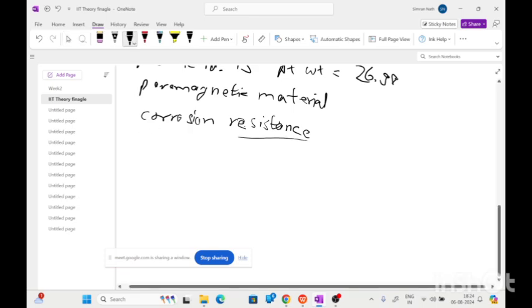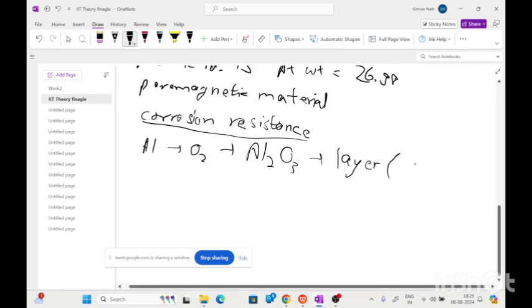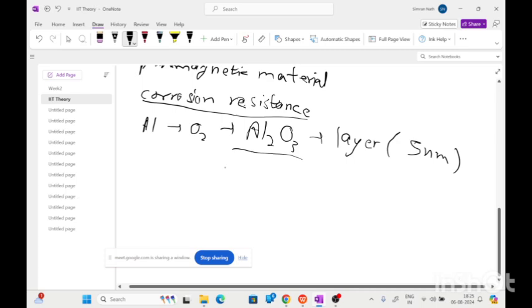So how does aluminium have high corrosion resistance? Aluminium has a tendency to react with oxygen to form aluminium oxide, Al2O3, readily. When the Al2O3 layer forms on the aluminium, it is a very adherent and impervious layer of thickness 5 nanometer. The adherent layer of alumina inhibits further corrosion of the component, thereby providing good corrosion resistance.